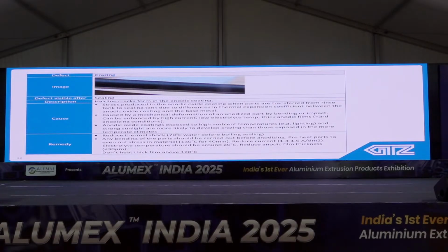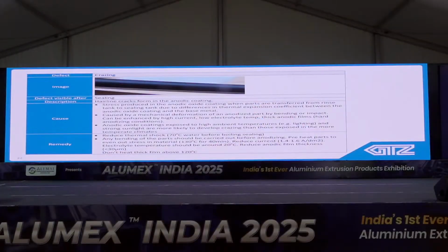Crazing. Crazing is cracking, or hairline cracks, in the anodic coating. If there is a certain temperature change or any shape change, there is a crack because the thermal expansion of aluminum and aluminum oxide is not the same. Always the thermal expansion of metal is more. So if there is any deformation or any certain temperature change, there will be stress and cracks will form to release the stress. So thermal shock has to be reduced.